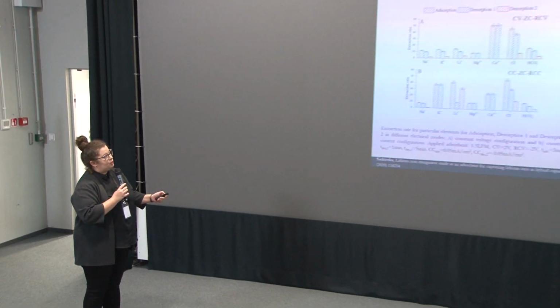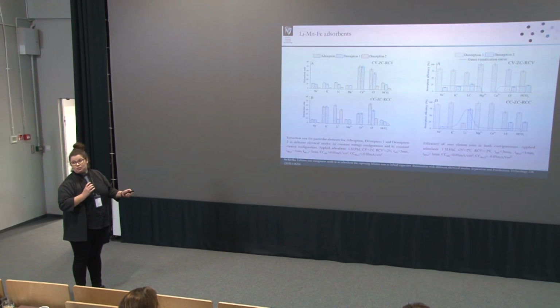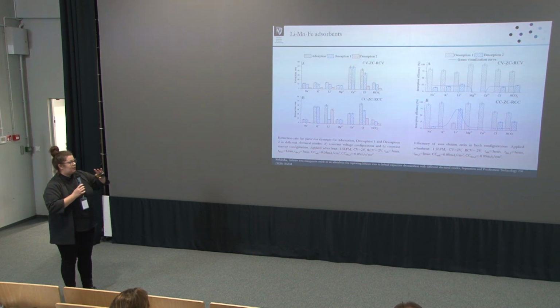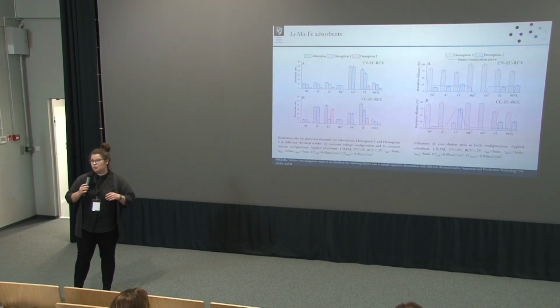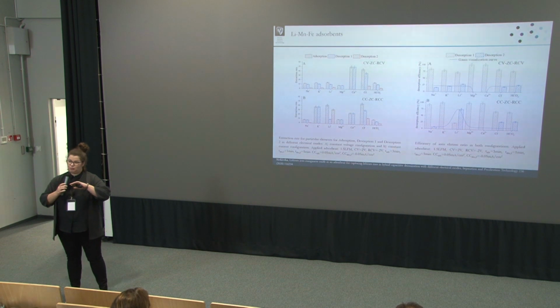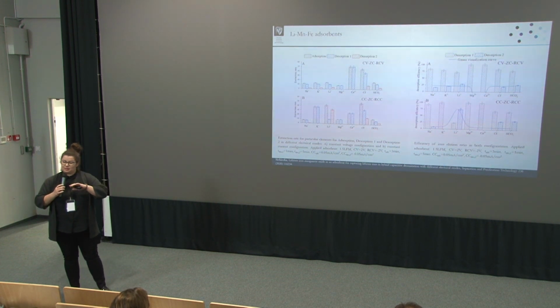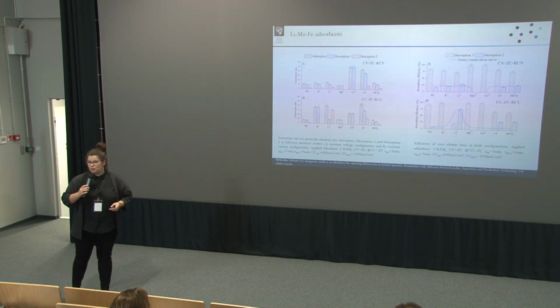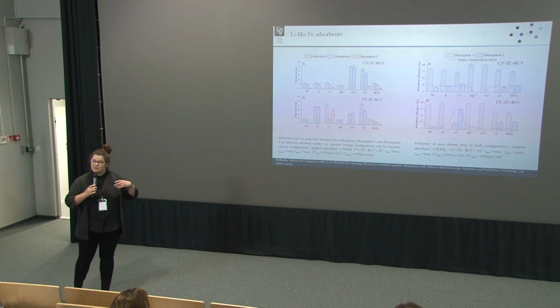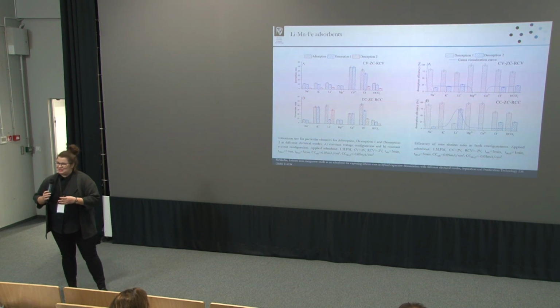The composition of the solution was the same. However, the difference was in the electrical mode. This is the charge voltage, zero charge, reverse charge voltage. By applying different modes, you can have stable voltage, or you can have stable current. This is a huge difference with the pushing, with the external forces, trying to move the cations from one side to the other.